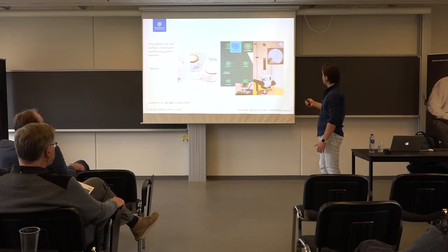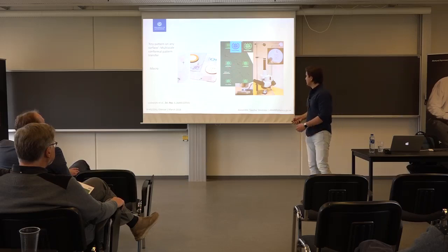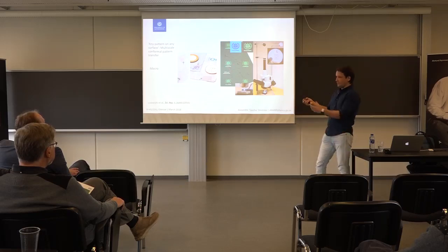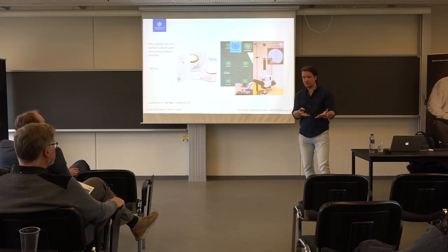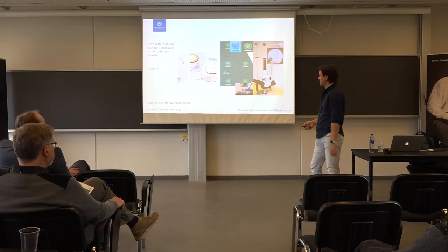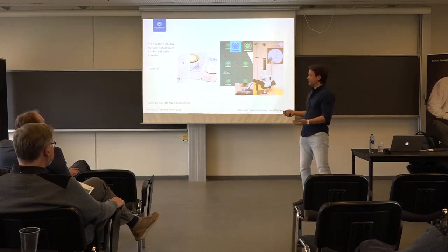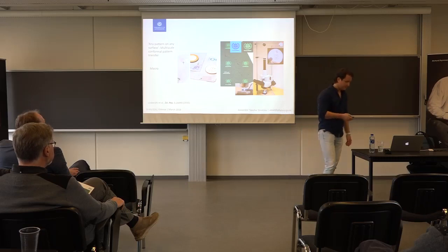No Photoshop, that's just the picture. And you see it's the logo of Chalmers University of Technology. It is projected from the size of like 50 microns here onto the wall at a 5 centimeter scale. So actually, that is of course written with E-beam lithography, but the pattern survives, could be transferred to really nasty substrates, really rough substrates, and it can even function like a projection mask.